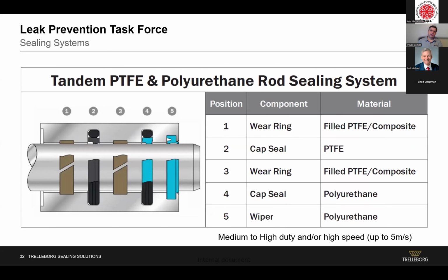Now, if you want to go into a little more of a premium solution, or for unique applications, if it's medium to heavy duty, but also high speeds, for example, you might use a PTFE solution. These can be really effective, low friction, low wear type seals that can be used for really high speeds. So that can be a good option. In this system, it's combined with a polyurethane secondary seal to still provide good leakage control, and those can really balance each other quite well. So we've seen a lot of success with this type of system as well.